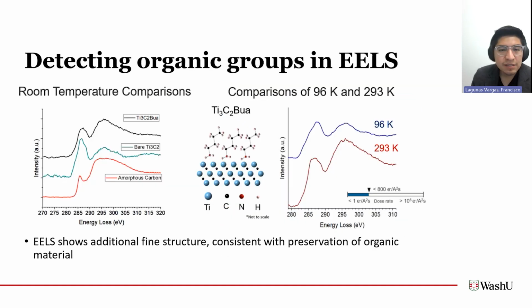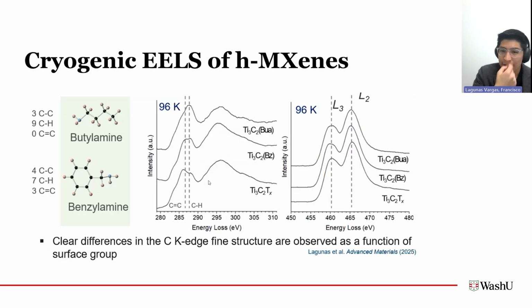But if we look at samples that we expect to be preserved, then we can go back to our EELS measurements and start getting an idea if we're able to detect differences in the bonding. So here is our BUA sample, which is composed of a lot of carbon-hydrogen bonds and carbon bonds. And you can see in red is the spectra that we acquired at room temperature, and then blue is the spectra that we acquired at liquid nitrogen temperature. And clearly there's a lot more fine structure, much better signal quality at cryogenic temperatures. We can quantify this, which is pretty exciting.